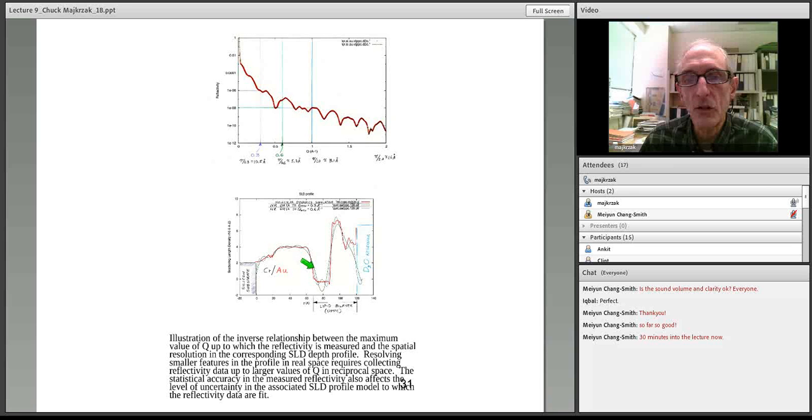And so you can secure this very thin, of the order of 50 angstrom, lipid bilayer to the surface, and then deuterate one leaflet, the upper part of the bilayer, and the lower part of the bilayer can be hydrogenated, and that gives us very large scattering length density contrast. And this can be placed in close proximity adjacent to an aqueous reservoir, for example.